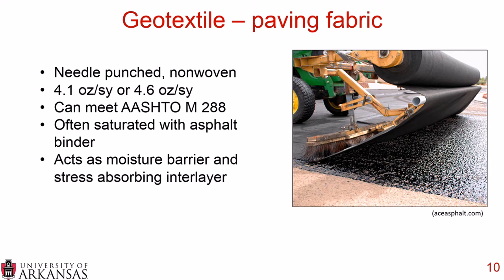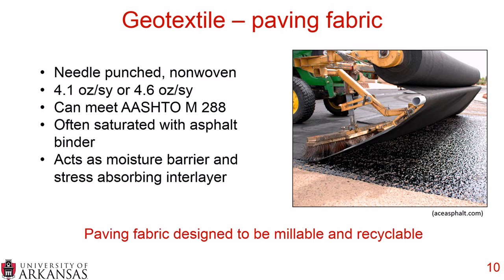You can see here it's being placed on an asphalt binder, and it's often saturated with asphalt binder. And this not only allows it to be a stress absorbing interlayer, but with this absorption, it can also act as a moisture barrier. Now, one of the common questions about this material is, can you mill it later, and can it be recycled into future mixes as reclaimed asphalt pavement? And there are paving fabrics that are specifically designed to be millable and recyclable, but that is something you definitely want to investigate before placing any particular brand.